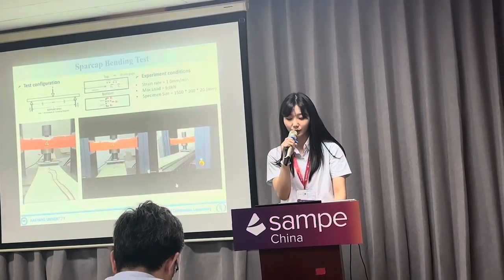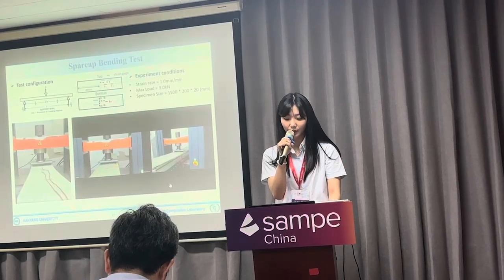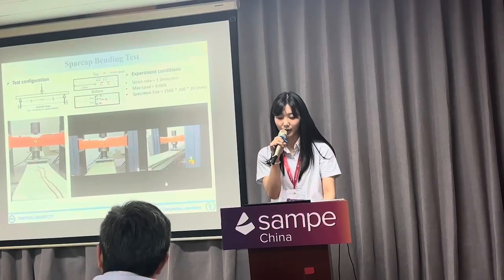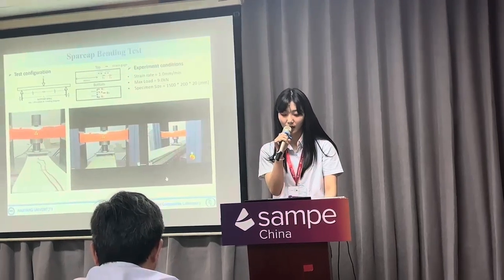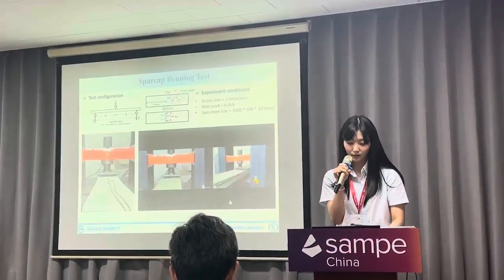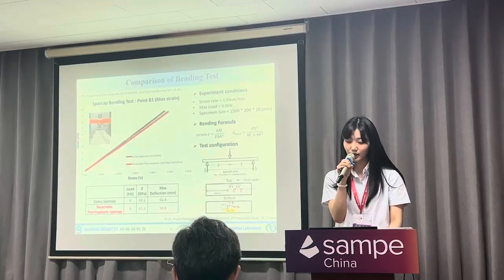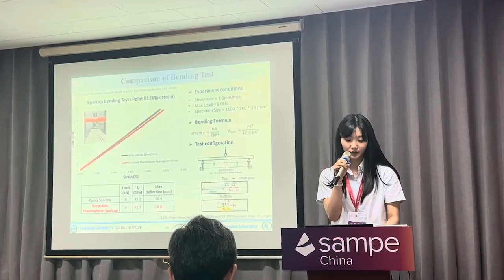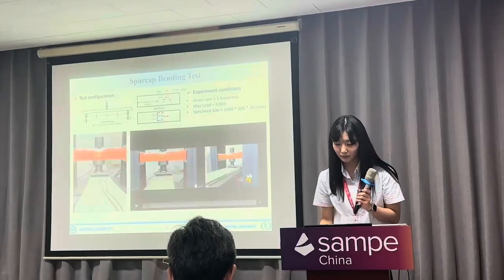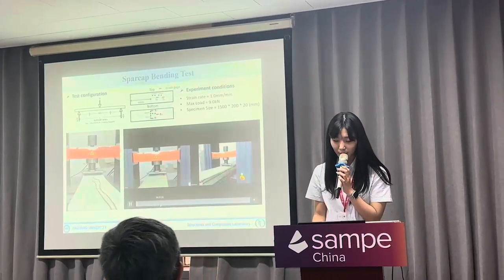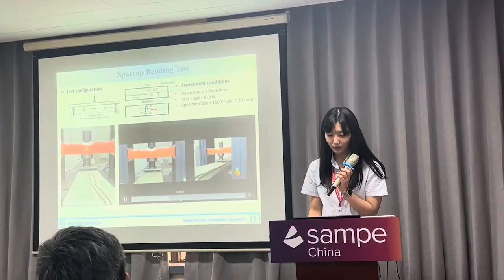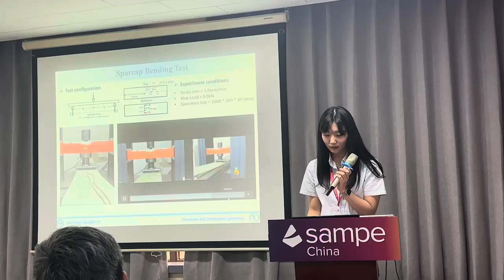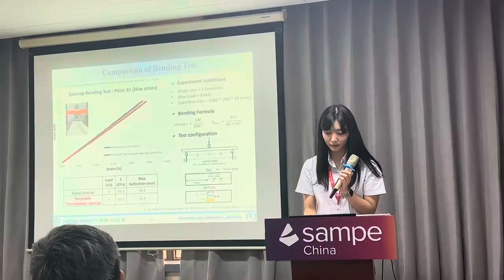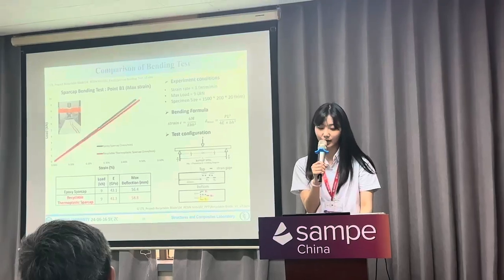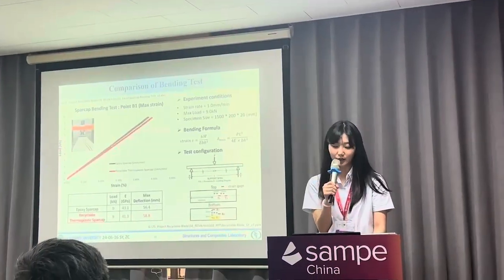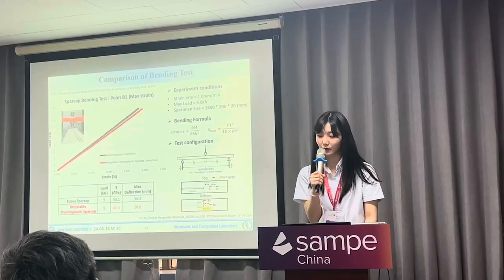After the full-scale infusion, we also conducted the spar cap infusion and performed a 3-point bending test using a UTM and compared the DOE PMMA and epoxy spar caps. As a result of the experiment, the bending results were measured similar to what we predicted. This is the process of 3-point bending. Compared to the existing epoxy system, it was confirmed that the mechanical properties of the DOE PMMA are very similar.